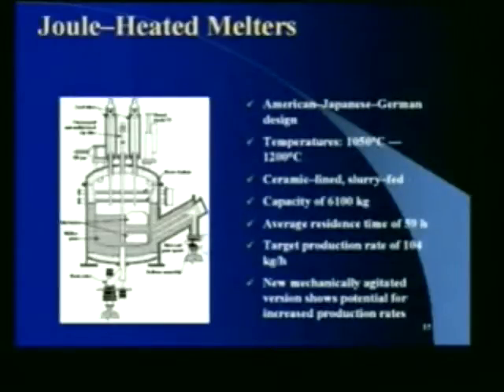Temperatures are typically 1050 to 1200. They're ceramic lined and slurry fed. They typically have a capacity in the reactor of about 6,100 kilograms. It takes about 59 hours of residence in the melter, with a production rate of 104 kilograms per hour.